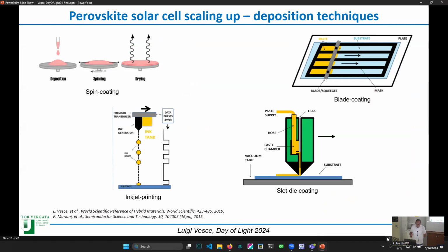These are typical deposition techniques for thin films. Spin coating cannot be considered a scalable deposition technique because of the size limitation and because of the material wasting, since you put more material than you need for the process. So generally one should work on a different process, such as blade coating or slot die coating, that are quite similar.